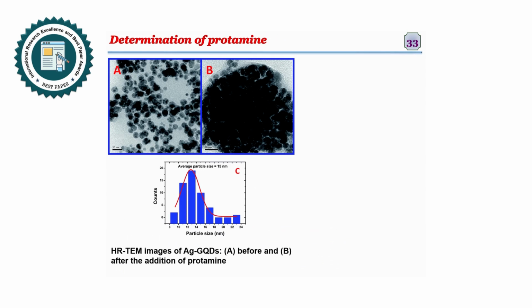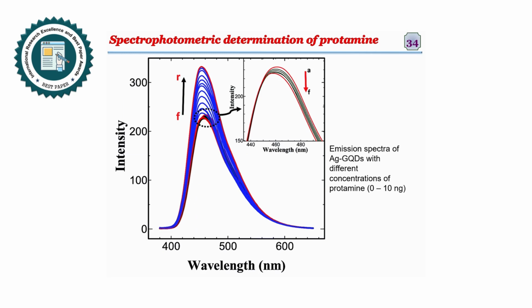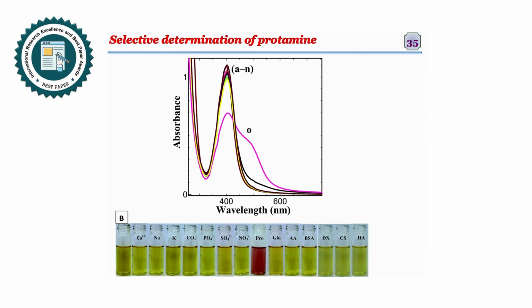So this is for AgGQDs. This is after protamine is added, and this is the aggregated structure, and hence the size of the nanoparticle is increased from 9 nanometers to 15 nanometers. It is evidenced from the analysis, and the emission intensity also decreased after the addition of certain protamine, and after that the emission intensity is drastically increased, because after a certain addition the silver nanoparticles are bound with the protamine, and there is a complexation. After that the silver nanoparticles are free from the GQD surface, and hence excess concentration of protamine leaves the GQD surface free, and the emission is retained. So here is the selective determination of protamine. The synthesized AgGQDs are highly selective towards the determination of protamine against other possible interferences.